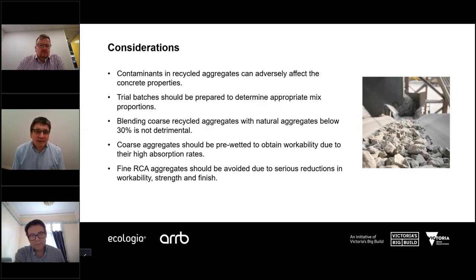So one of the barriers is potential for contaminants in these aggregates, and as Tony mentioned before, if we manage our stockpiles of recycled materials to the highest degree, we can avoid, I think, the costs of mismanagement of stockpiles of around $163 million. So contaminants are a key issue. One of the ones in recycled crushed concrete that we're quite good at managing is asbestos contamination. And in fact, while Victoria's been using recycled concrete aggregate for maybe 30 years, Western Australia Main Roads Department is only just allowing it, and they were too concerned about contaminants. So that can be a barrier.